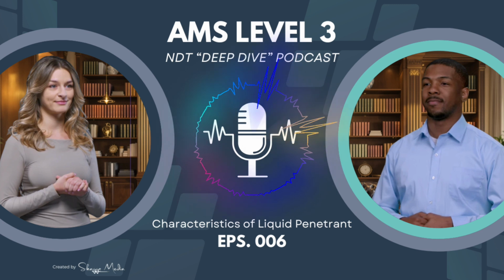And there's actual physics behind that limitation, isn't there? Something called the Beer-Lambert law. That's right. It's a fundamental law in optics. For these visible colored penetrants, the amount of light the dye absorbs, which is what gives it the color we see, depends on a few things. The dye's inherent ability to absorb light, its concentration, and critically, the thickness of the layer the light is passing through.